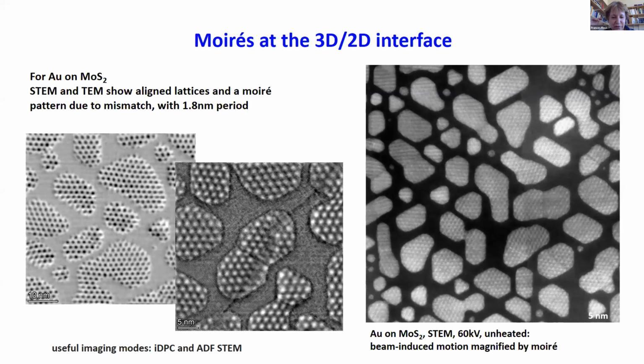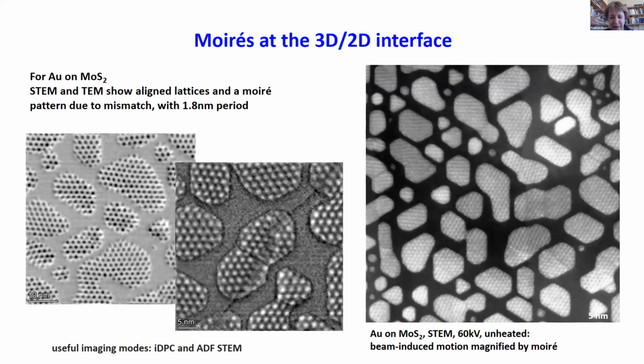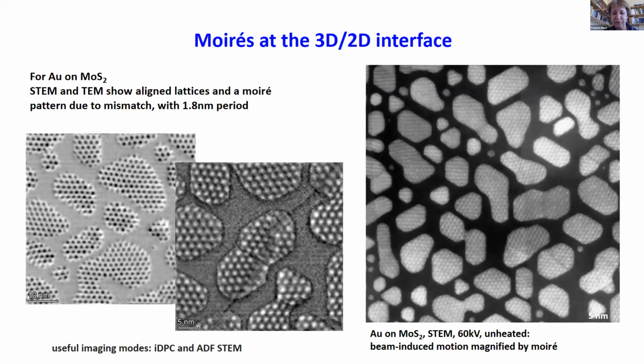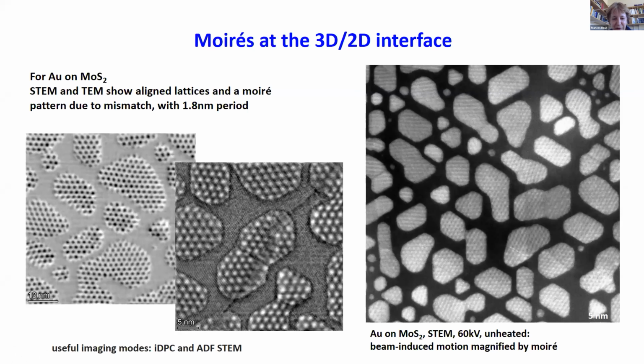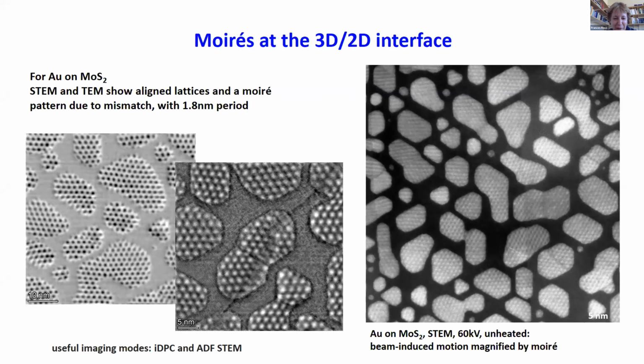So whenever we're looking at two crystals, in a column, one on top of the other one, the electron signal will respond to the alignment of those two crystals such that they go in and out of phase as you move across the sample. So this moiré pattern, we can analyze it to show that both the gold and the MoS2 are unstrained. There's no deformation of the gold because it's growing on this unmatched crystal substrate. It just grows completely happily, but it does talk to the MoS2 because you can see that each one of these islands has the identical orientation of its moiré pattern.